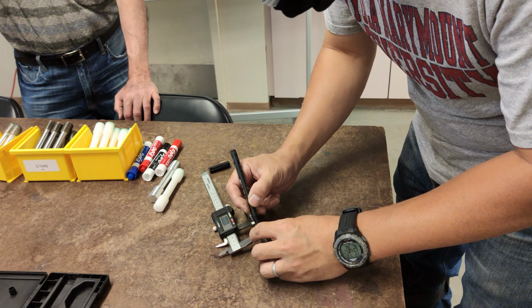So he measured the diameter. The area will be pi d squared over 4, and then he made a mark of 1 inch along the gauge, or along the length of the sample. Here is another example of the measurement procedure, measuring at least 3 positions at the middle area of the sample. Record the results, then calculate the average. By the way, don't forget to zero the caliper after you turn it on.